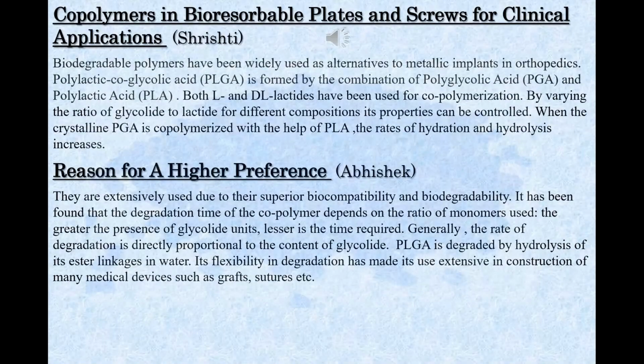Copolymers in bioresorbable plates and screws for clinical applications. Biodegradable polymers have been widely used as alternatives to metallic implants in orthopedics. Polylactic coglycolic acid (PLGA) is formed by the combination of polyglycolic acid (PGA) and polylactic acid (PLA). Both L and DL lactides have been used for copolymerization. By varying the ratio of glycolide to lactide for different compositions, its properties can be controlled. When the crystalline PGA is copolymerized with PLA, the rates of hydration and hydrolysis increase. I would now request Abhishek to continue further.